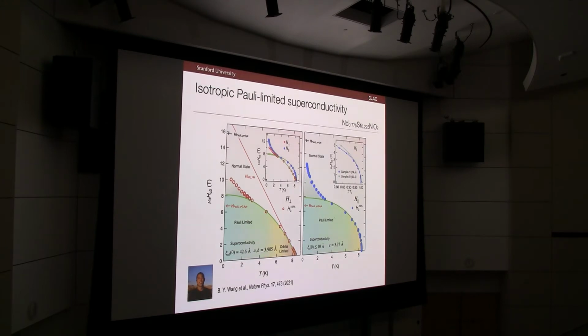A second aspect that is quite puzzling is that most of this upper critical field seems to be Pauli-limited. That is to say that the suppression of superconductivity is not coming from the pairs running around, so orbital depairing, but rather it seems to be set on the scale of the Zeeman, right? That I flip one of the spins, the anti-parallel spin configuration of a Cooper pair.